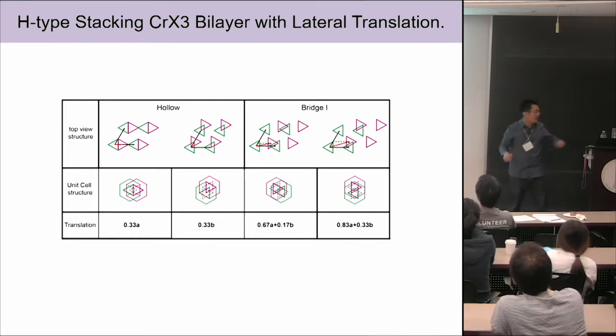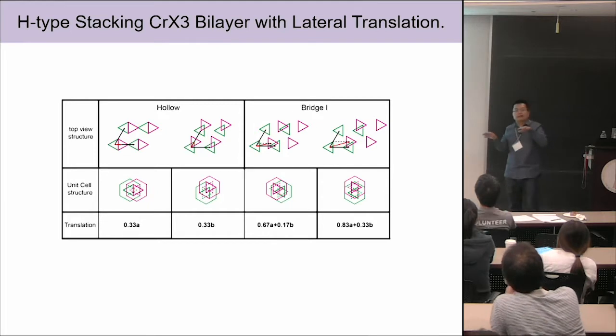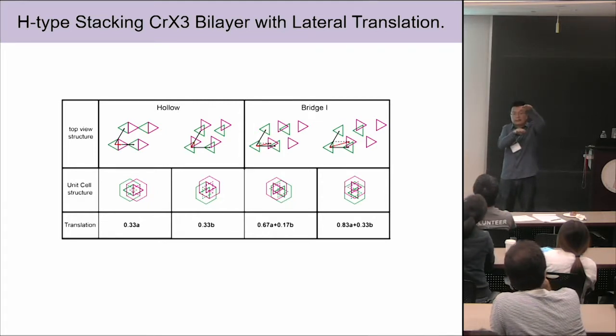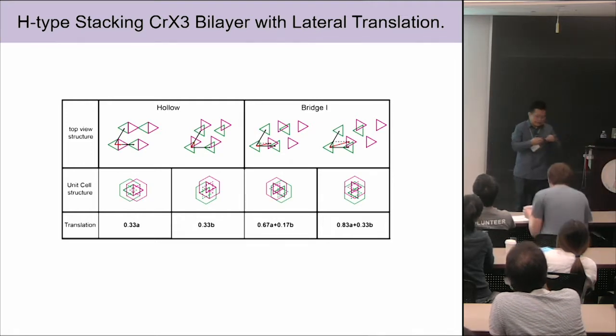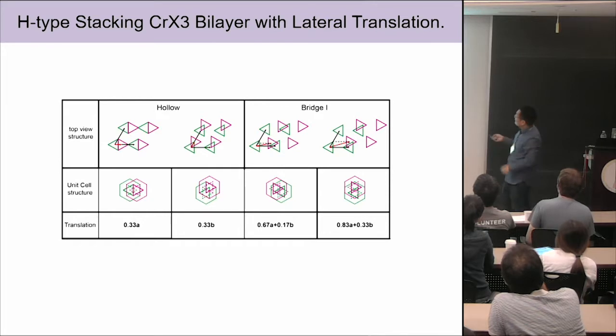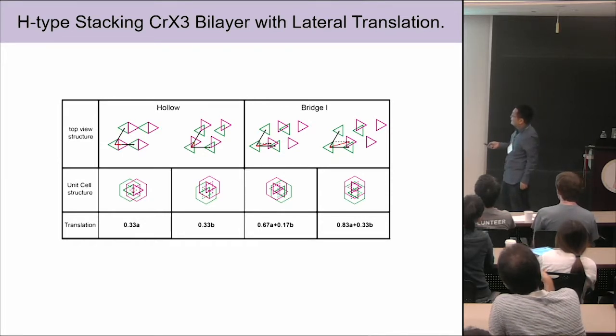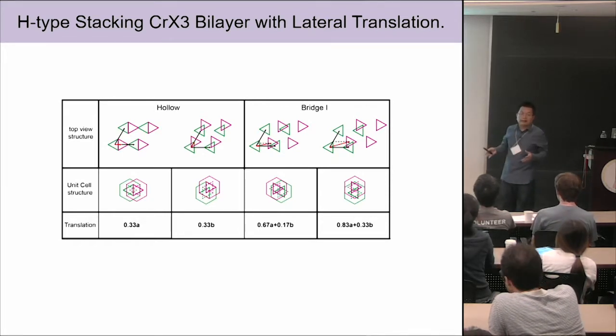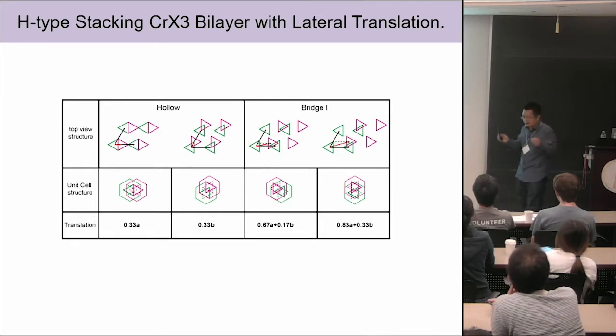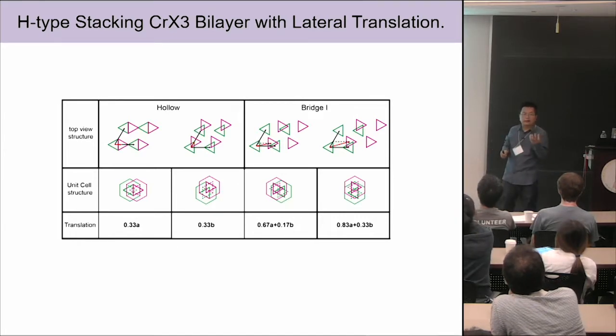Remember? But for H stacking, for the single layer, the top 3 iodine atoms and the bottom 3 iodine atoms actually orient in the same direction. There's no 180-degree rotation, okay? So with that, there's another structure which is called H-type stacking. And nobody discusses it, right? Because all the papers we see and all the X-ray diffraction says this crystal should be in the R stacking, but there's no H stacking.